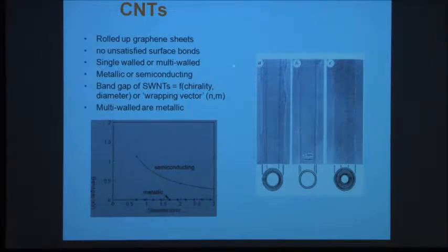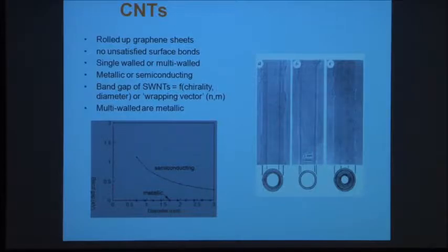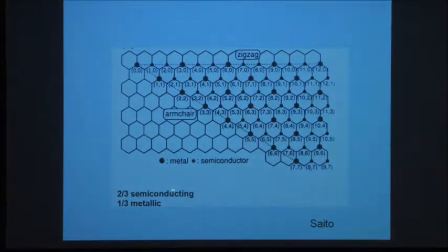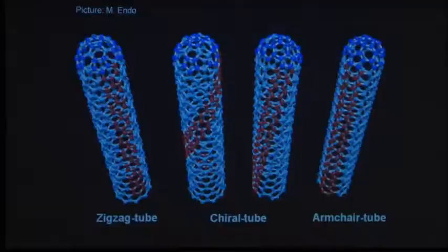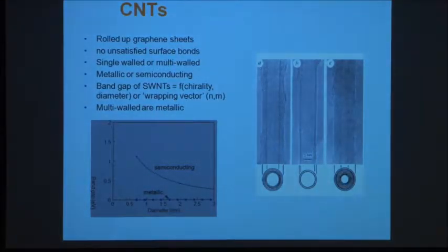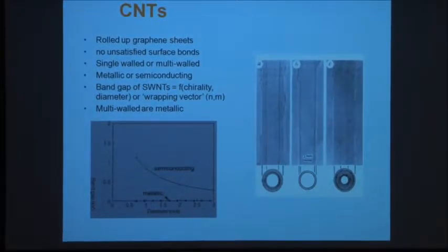They can be metallic or semiconducting, and the band gap of single-walled nanotubes is dependent on the chirality, but it's also dependent on the diameter. So if you look at a nanotube and you go down in diameter from 3 nanometers down to 1 nanometer, the band gap goes up from about 0.4 to 1.1. Generally speaking, multi-walled nanotubes are always metallic-like, and that just goes back to that figure, which says that once you've got three walls, one of them is going to be metallic, and that will dominate. So once you've got above three walls, generally speaking, the tubes are metallic-like. Everybody happy with that? So single wall, multi-wall, they can be metallic, they can be semiconducting, but the multi-wall ones tend to be metallic-like. The band gap of the single wall depends on the diameter, as well as the chirality of bonding.